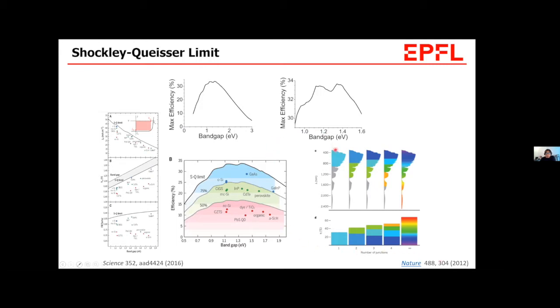And if you can make multiple junctions, you can increase the efficiency, of course, as you can see. If a single junction solar cell absorbs this part of the solar spectrum up to around 900 nanometers, the cell can attain around 31%. And if you stack the cells using absorbers with different band gaps in an ideal way, I can achieve 68% in principle. This type of device is what we call multi-junction solar cells or tandem solar cells. This will be dealt with the day after tomorrow by Professor Nazeeruddin, in the tandem session.